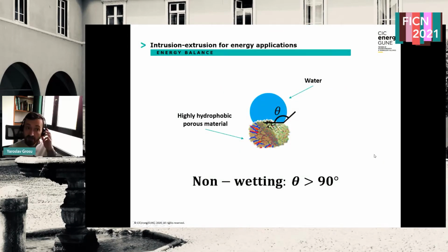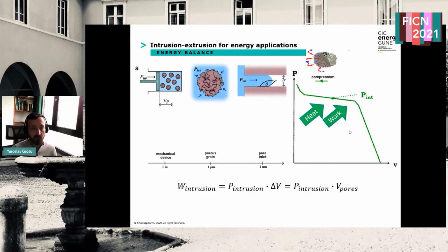Okay, so to oversimplify the concept of intrusion-extrusion, you have to imagine any nanoporous material which is highly hydrophobic, meaning that the contact angle with water is at least 90 degrees or more. So those systems are interesting because due to high hydrophobicity of the porous material, the pores tend to be dry or empty under ambient conditions. However, one can force the water inside the pores by applying some pressure to the system. So particularly, for example, which is often the case, by putting the porous grains of porous material immersed in water and applying some pressure.